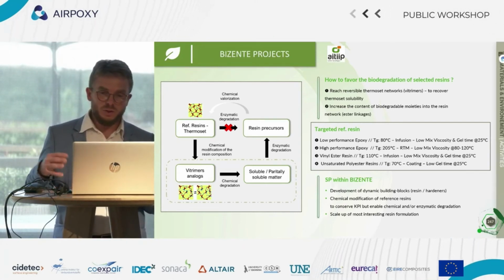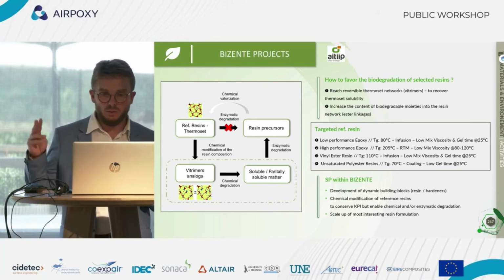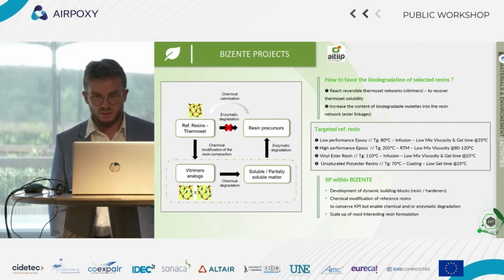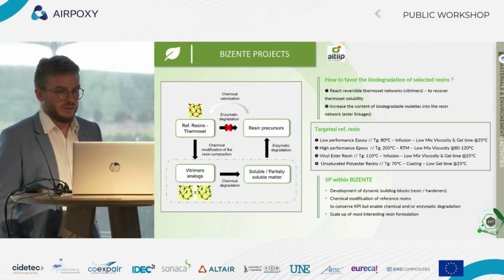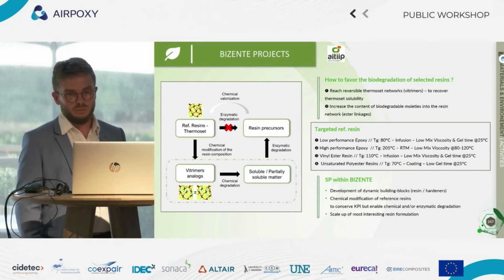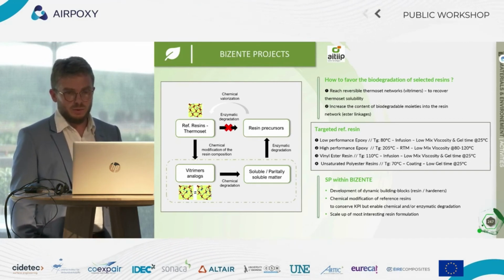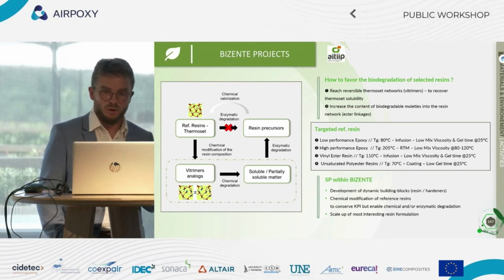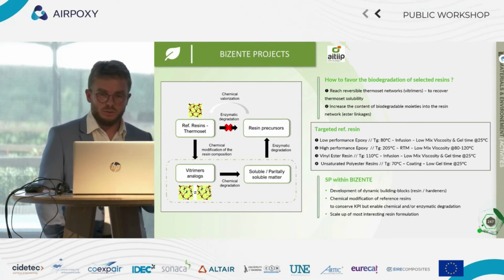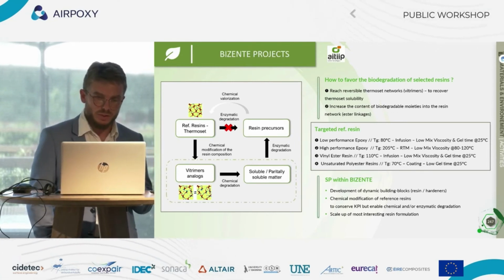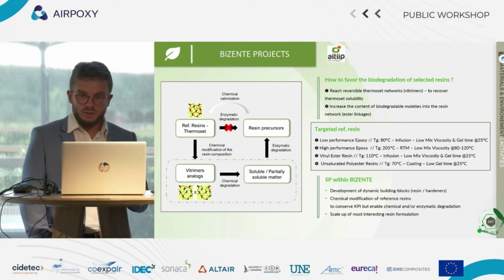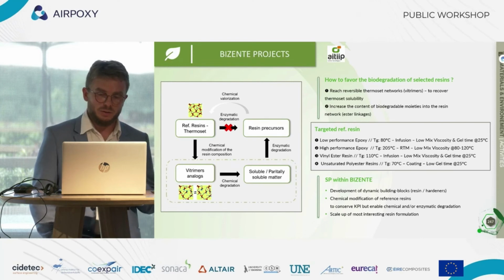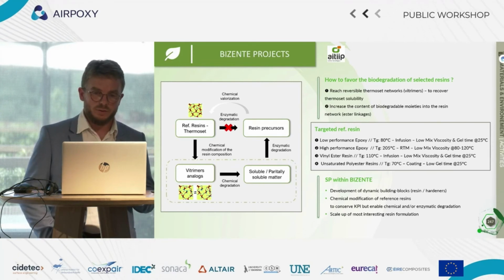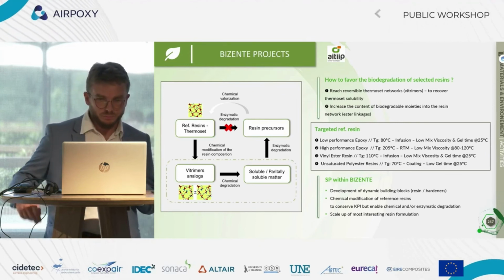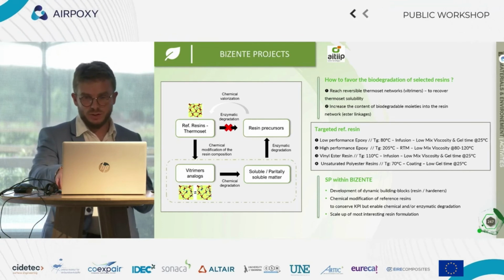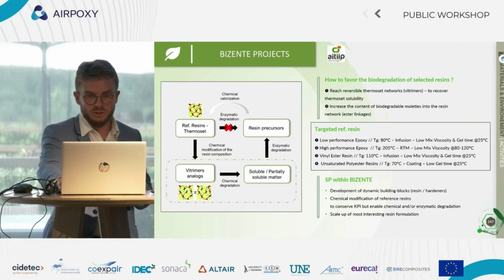So in the scope of this project, we addressed 4 different resins: two epoxy, one I would say low TG, 80 degrees, one high TG at 205 degrees, one vinyl ester resin, and one unsaturated polyester resin. So the good news at this point of the project, we are at month 24, we found a reversible alternative to these 4 resins. And we are, for instance, quite happy to have a Vitrimer with a TG about 205 degrees with the other specifications. And now we produce this molecule. We also work on the chemical degradation process, and now we provided the samples for the enzymatic degradation partners for further evaluation. So in the scope of this project, it was the same methodology that the one I explained about how we develop the resin in order to reach these objectives.